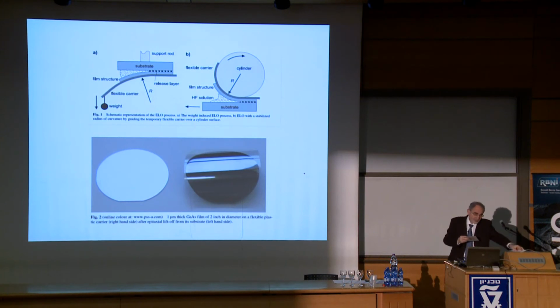Let me show you the ones that are made by Alta. This is essentially an industrial process now. And they basically have epitaxial gallium arsenide films coming off 6-inch wafers and just pulling them off. And it takes a very short time just to pull off a wafer, and then they reuse the substrate. In this way, the cost goes away. And so I'll show you these afterward. Here's one that has been assembled into a small panel. And you see it's just wavy, flappy. You wouldn't think this is a single crystal, but when it's very, very thin, it's very flexible, surprisingly so.